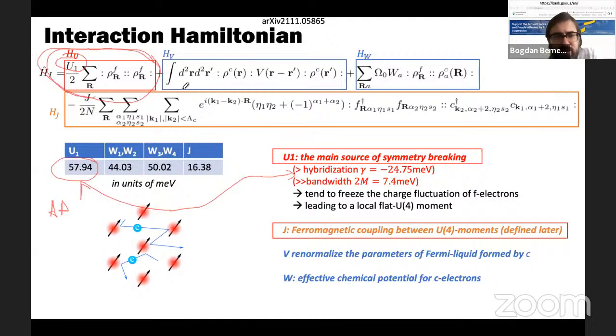Then you have some other Coulomb scale between the conduction electrons. We can just neglect this. This is important for different fillings. You have a density interaction between the f-electrons and the c-electrons. This density interaction actually just acts as a chemical potential for the c-electrons. And the term that's the most important for the topology of the correlated insulator is what will be a ferromagnetic Hund's coupling between a U(4) spin of the f-electrons and the c-electrons. So most of the physics of this model can be understood with just these three terms plus the three terms with the arrows, plus the interaction plus the heavy fermion single particle physics. And let me just give you some example.